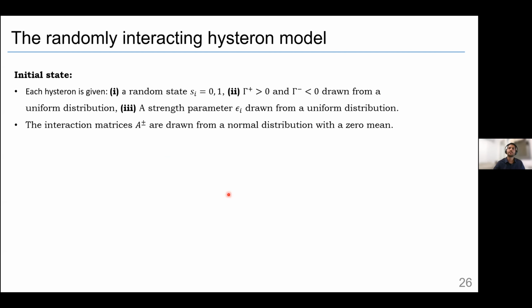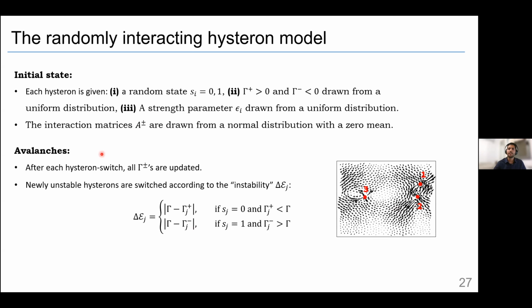So briefly about the models that we use. Our model is random. Everything is random. The state of the hysteron is random, gamma plus and minus random. The strength is also random, and the interaction matrix. Because we have interactions, we need to discuss avalanches, meaning that after we update gamma plus and minuses, there are some other hysterons that become unstable, and we switch them in order, meaning that the most unstable one will be switched first, and then we repeat the process until everything is stable.